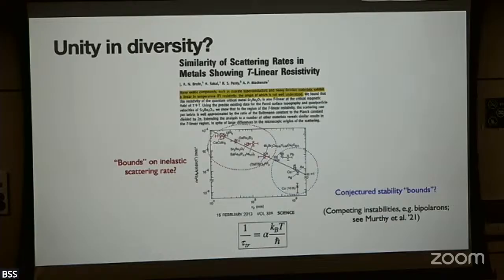So like Peter was showing during week 1, you measure omega dependence of conductivity, you get some Drude-like peak that has the width, that's the optical scattering rate. But unfortunately, optics requires much more effort. Again, to the experimentalist students in the audience, just try to come up with new methods to do optical conductivity across all kinds of interesting compounds. So in the absence of optical conductivity measurements, well, what is the other thing you could do? So here's what they did. So they assumed that you can describe the DC resistivity using Drude-like model. Okay, maybe that's oversimplification, but you do the best you can.